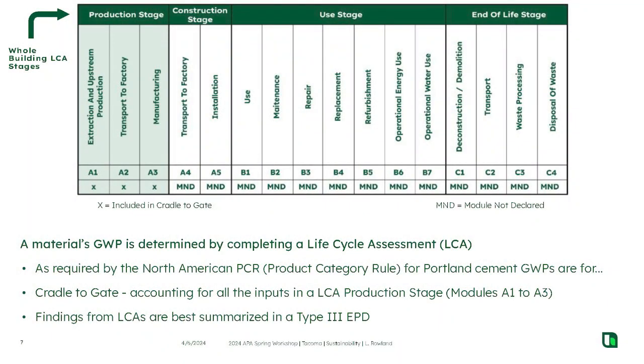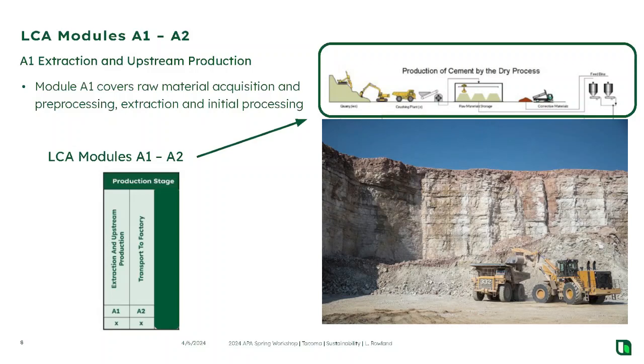So this is putting that A1 through A3 on a chart just to kind of give you the percentages. So my extraction is over here in my quarry. That's my A1. Transfer from the quarry to the plant, you can see, I'm down around 3%. Very minimal impacts as far as my global warming potential, my carbon footprint, my embodied carbon for these materials. I'm using these terms all interchangeably. But the idea is how much CO2 is associated with that process. So very little back in the A1 and A2.